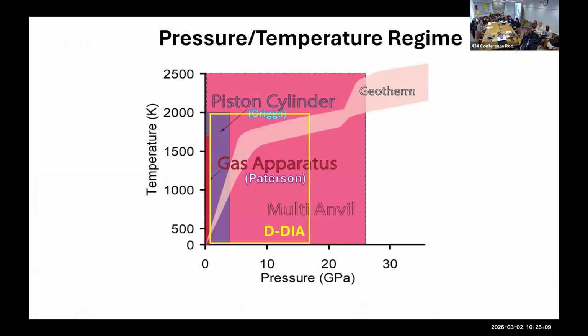This is just showing pressure versus temperature for a few different apparatuses. So you have gas apparatuses, they're very hydrostatic, but they can't generate all that high of pressure. Piston cylinders are somewhat similar to this device, but they operate at somewhat lower pressure too. And then the D-dia, we can sort of reach this region. This is actually kind of optimistic, about 7 GPa, probably more around 10 is working operation, but you can push it higher under certain circumstances. And then you can get up to around 2000 Kelvin.